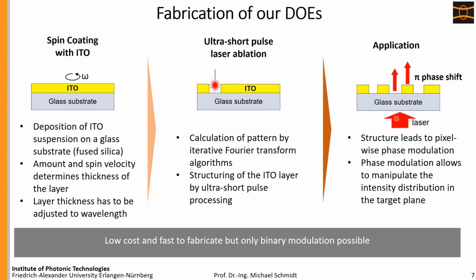So it's arbitrary. Nevertheless, of course, you cannot change it dynamically. If you have it once, then you need to use it. So this is quite a low-cost solution. It's fast to fabricate. It takes less than 2 minutes if everything's fine. But we only have a binary hologram, as you can see here, which is not so good for the efficiency. But we are quick, and for our preliminary tests that I'm going to show you next, this is quite a good thing.